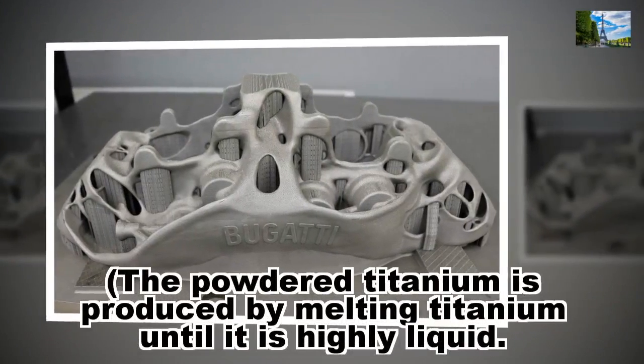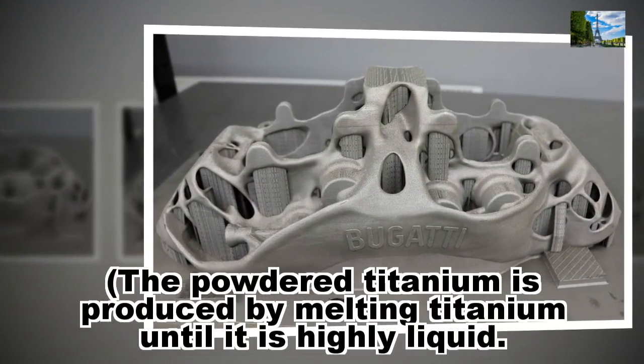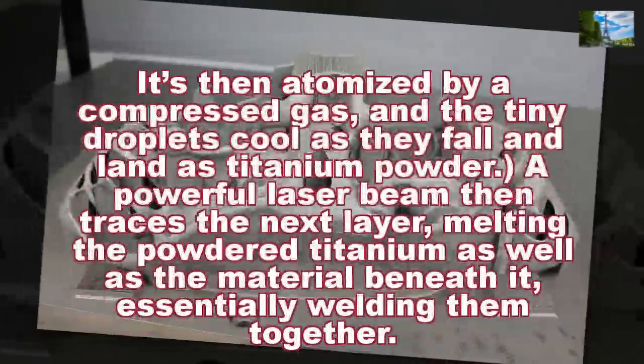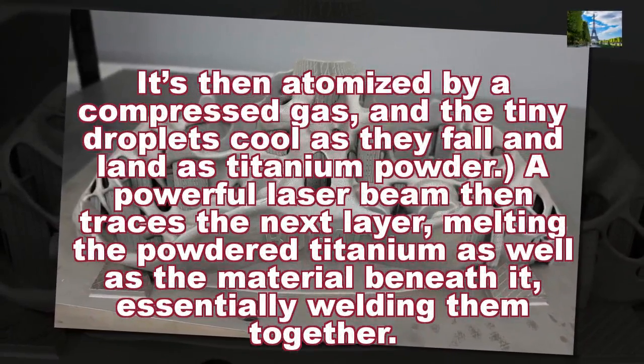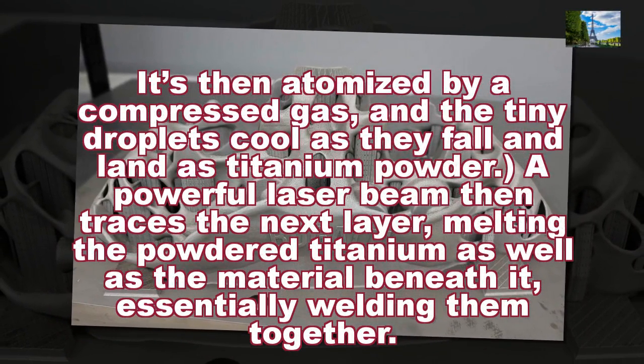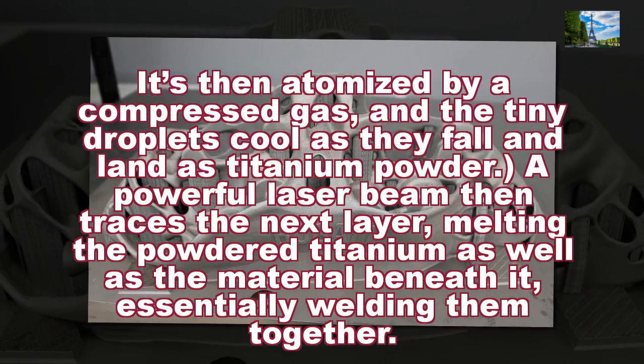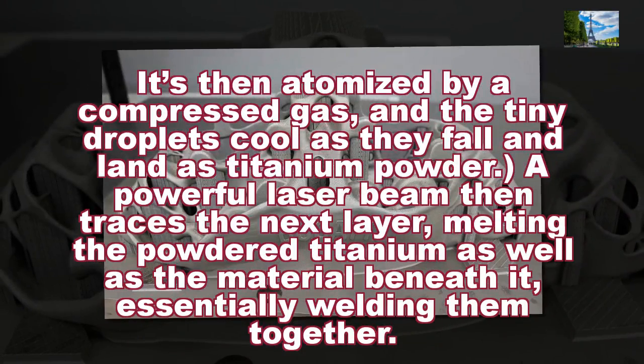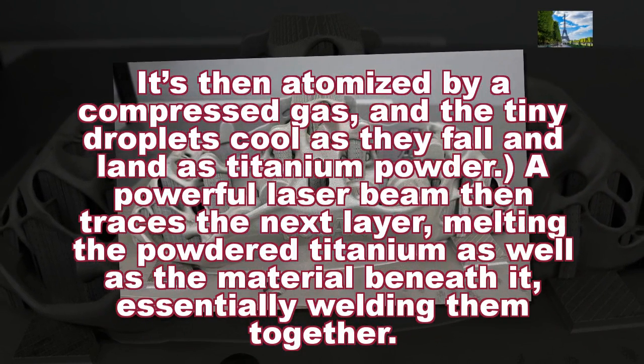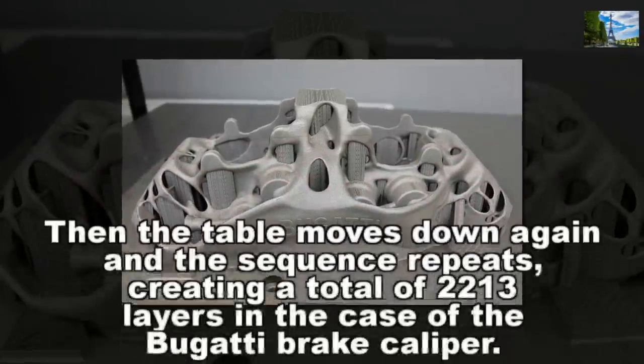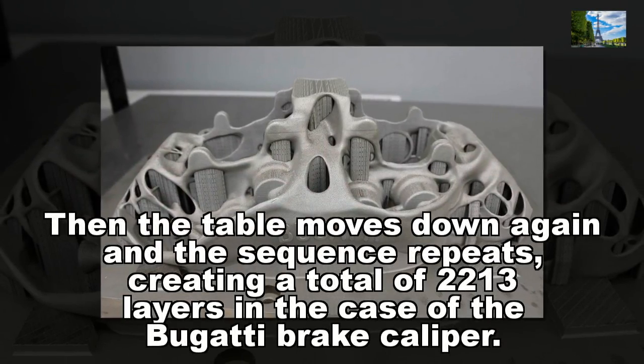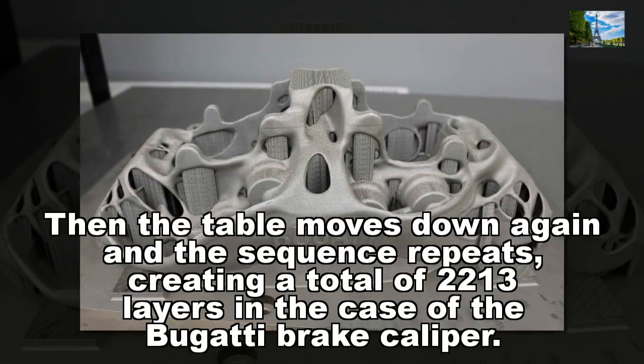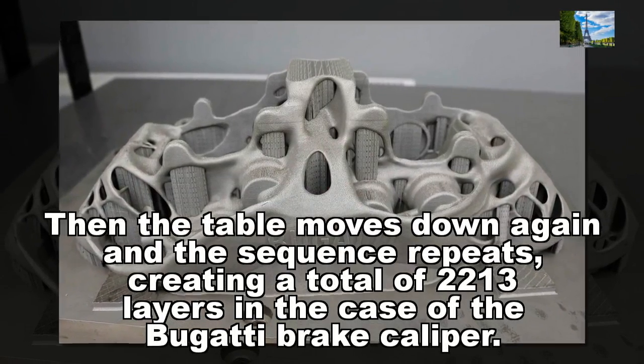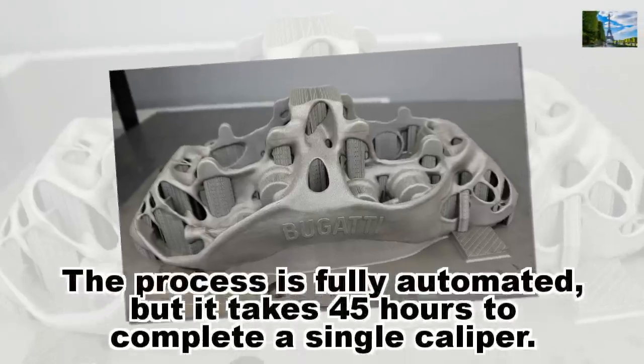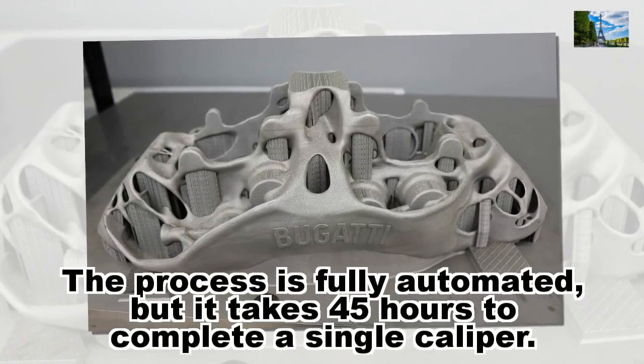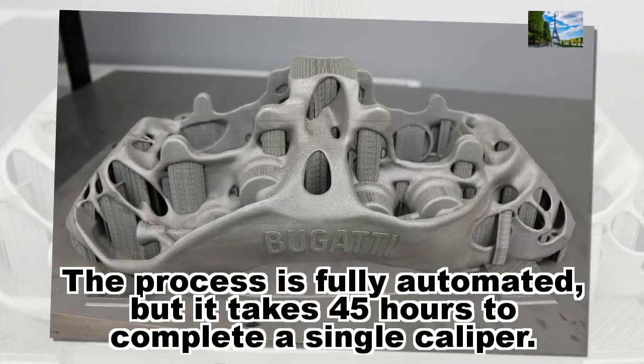The powdered titanium is produced by melting titanium until it is highly liquid. It's then atomized by a compressed gas, and the tiny droplets cool as they fall and land as titanium powder. A powerful laser beam then traces the next layer, melting the powdered titanium as well as the material beneath it, essentially welding them together. Then the table moves down again and the sequence repeats, creating a total of 2,213 layers in the case of the Bugatti brake caliper. The process is fully automated, but it takes 45 hours to complete a single caliper.